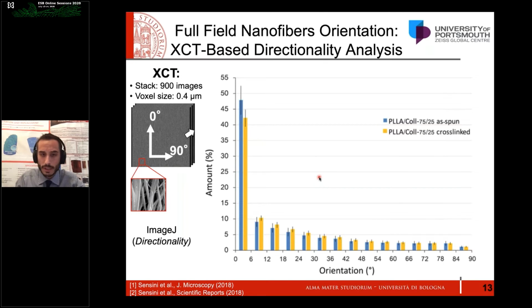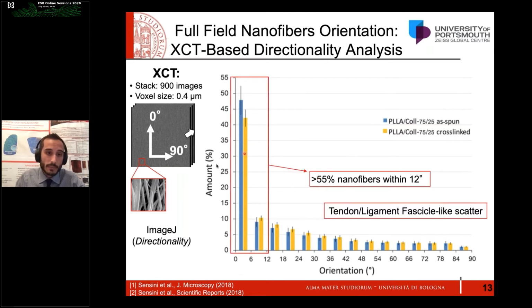You can see that basically the majority of the nanofibers resulted aligned in a range of 0 to 12 degrees, with a progressive physiological scatter to the circumferential orientation, as happens in tendon and ligament fascicles. Moreover, with these protocols it was also possible to see that after the cross-linking process we have a slight reduction of alignment of the nanofibers, due to the shrinkage that occurs after cross-linking.